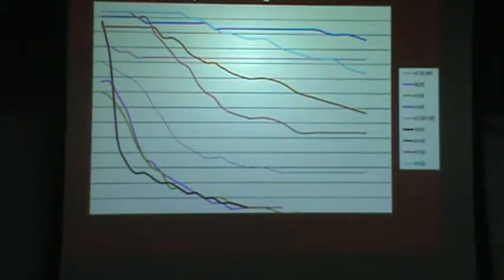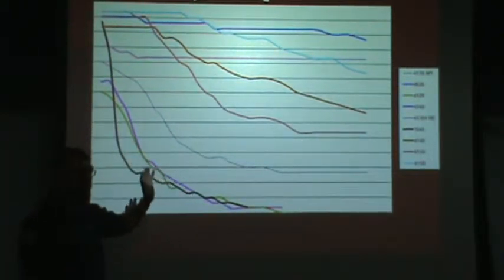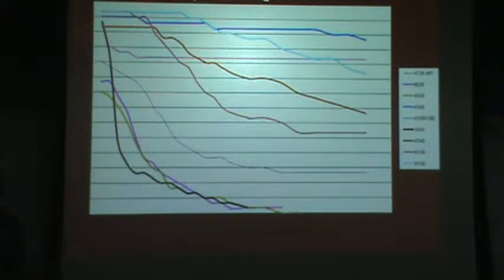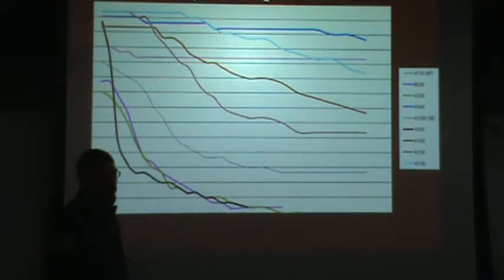Questions on that? Wait, so carbon content is a big factor, or? It's a big factor in the surface hardness, right? And right here at the very beginning. But once you get below the surface, the carbon is less important. It's still important, but at the surface, it's the dominant variable. And when you get further in, it's not dominant anymore.